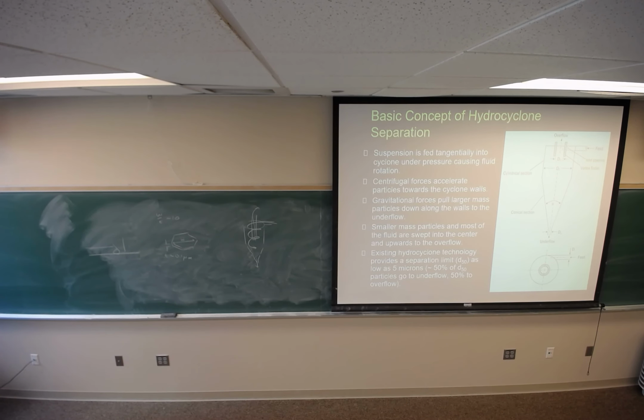You have a practical cutoff for size, which is around 5 microns, which is fine for our clay particles. Quartz particles that are 5 microns, we don't care about. But you're going to separate out the big quartz particles by hydrocycloning, and then you end up with your clay particles remaining in suspension, which is perfect.